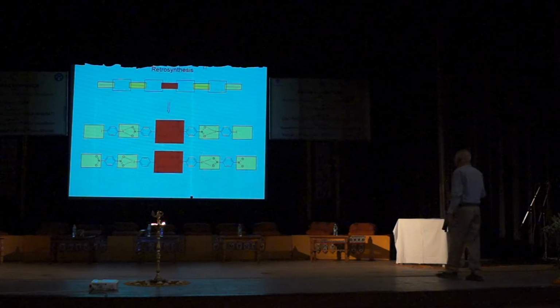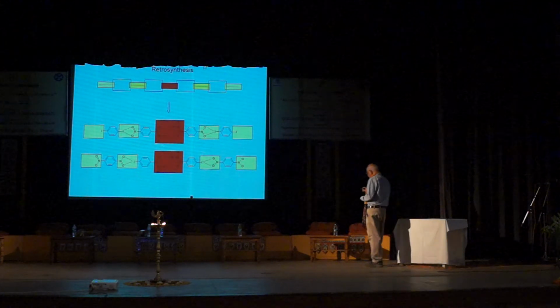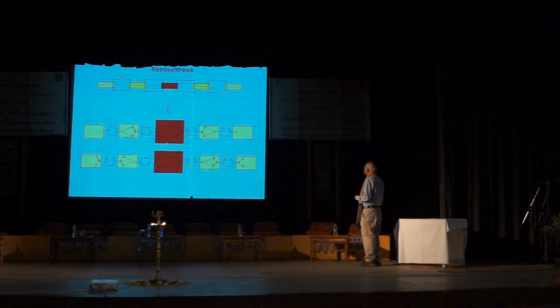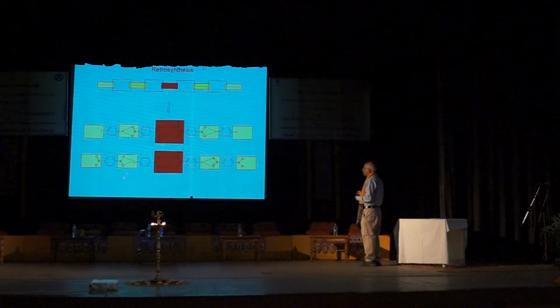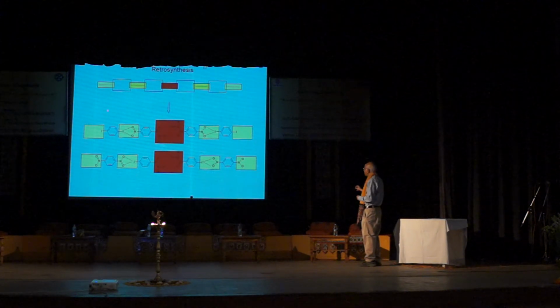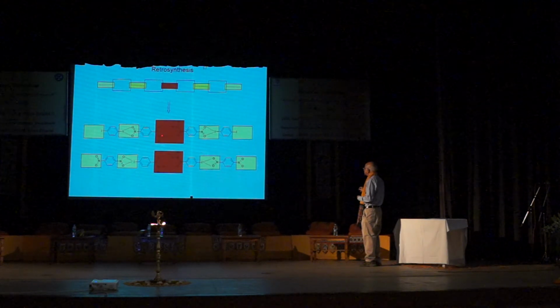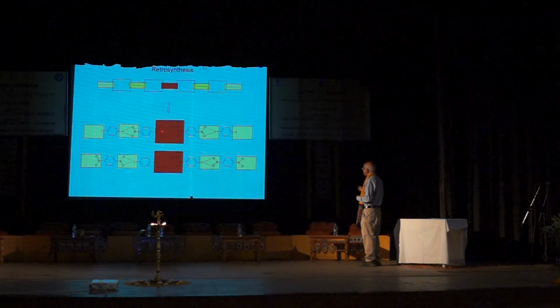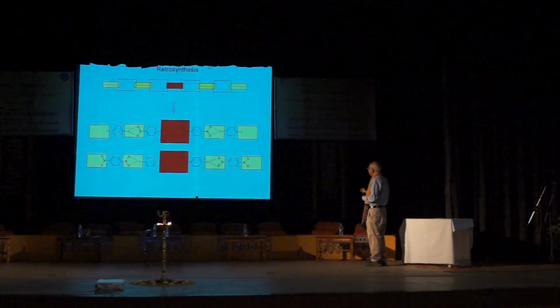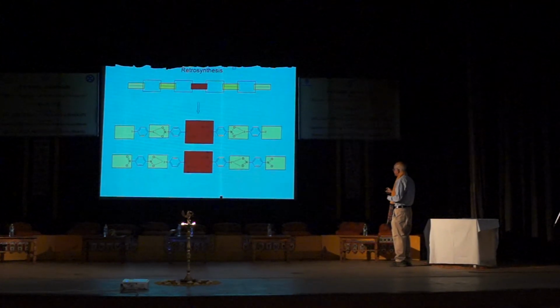So then what did we do? Go back to the amide. This red synthon is the amide dimer. This is the iodo-nitro dimer which, like the phenol, was insulated. So we've got two different kinds of synthons. Once again, this is a binary system. There is an amide with a diiodobenzene. Then there is an iodo-amide with dinitrobenzene. Both these got the same structure.